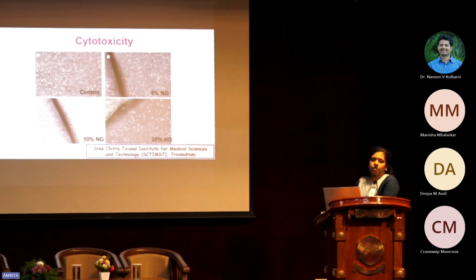So we also check the preliminary cytotoxicity evaluation to see whether the nanogel has any toxic effect. It shows that there is no toxicity up to 10 weight percentage, but at 20 weight percentage there is a slight or mild toxicity. But even at 10 weight percentage of nanogel, the TG is drastically decreased. So it is good for that application. In general, it's a preliminary study that shows that the reactive nanogel itself can be used as a plasticizer rather than using the toxic phthalate-based esters in many of the base matrices. So we are extending this study to different base matrices like PVC and PMMA and all. The studies are still going on.